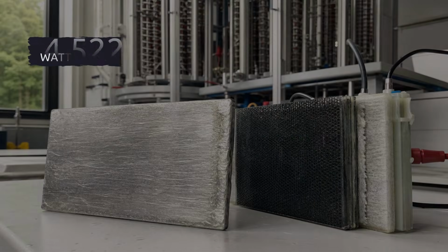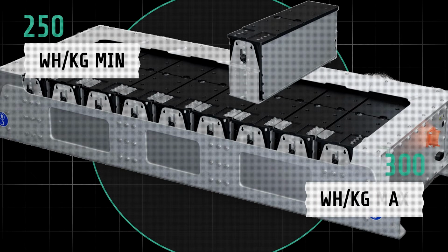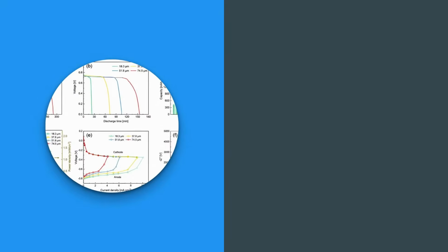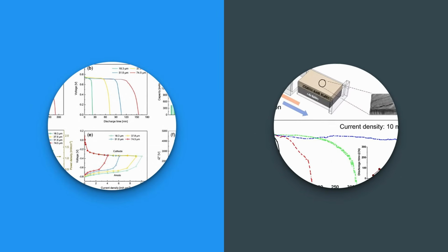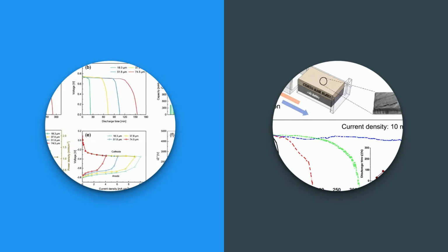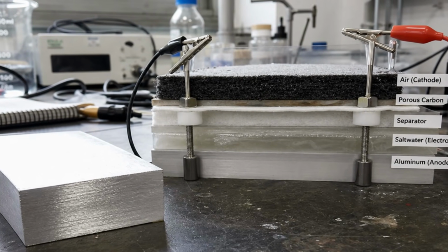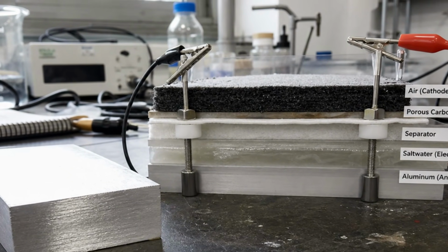Now the numbers. Theoretical energy density for aluminum air runs to 8,100 watt-hours per kilogram. Practical lithium ion sits somewhere between 250 and 300. Real aluminum air cells fall well short of their theoretical ceiling, as every chemistry does, but even a modest fraction of that figure is a very large number.